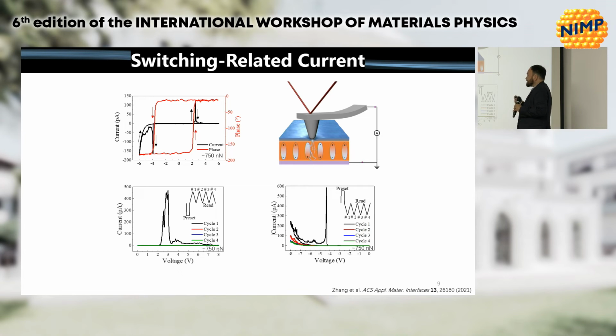Now, to illustrate that it's just happening when we're doing switching, we do a preset pulse, and then on the first pulse back, we expect there to be switching, and then we don't expect to see currents on the subsequent pulses because we're not switching anymore. So in that case, for cycle 1, we have a nice peak, and for all the other cycles, there's no current. So we're attributing this to switching-related current. But what we don't think it is the displacement current, as I'll explain. We think it's related to like an injection or a tunneling current.